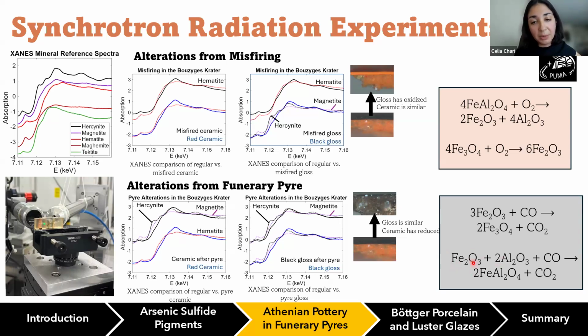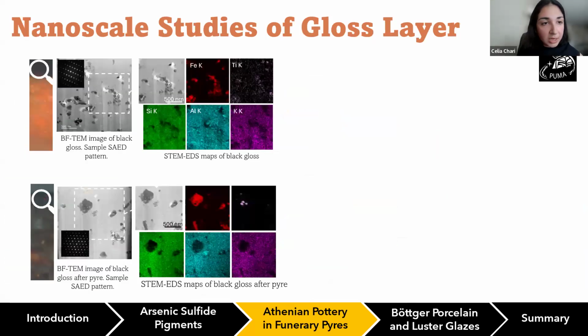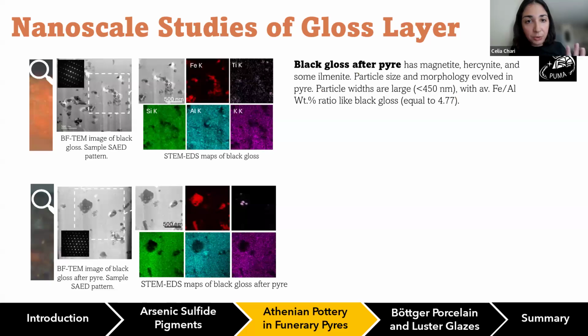So the iron oxide, the hematite, would have reacted with neighboring alumina components within the ceramic. So even though the gloss is similar according to the XANES analyses, we wanted to look into this question a little bit more closely using more localized studies with FIB-SEM and STEM-EDS. So we cut out different samples from these gloss layers, either the black gloss from the red, or the black gloss from the pyre. And we looked at these samples with TEM, and also we did EELS mapping to be able to look at the oxidation states of each individual particle within the gloss layer. And we found these general conclusions.